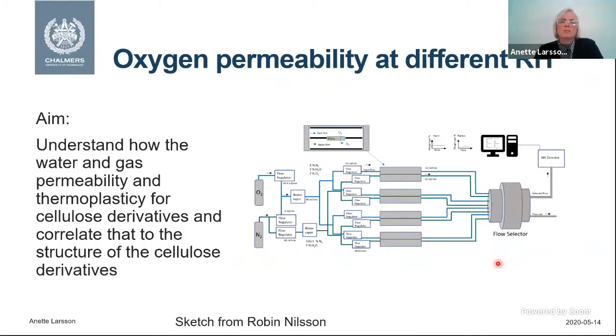So permeability is a super interesting thing. We are also now working with oxygen or gas permeability. We have started to build our own permeability measurement instrument, where we have the film and we flush the gas through on one side and measure how much oxygen, in this case, has reached the other side through the film, and determine that with the MS detector.